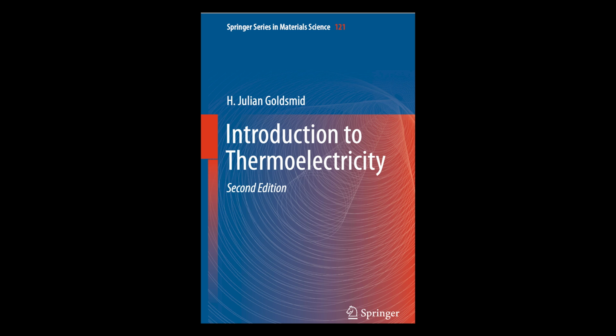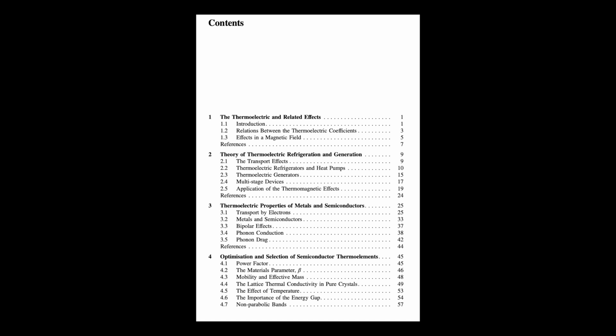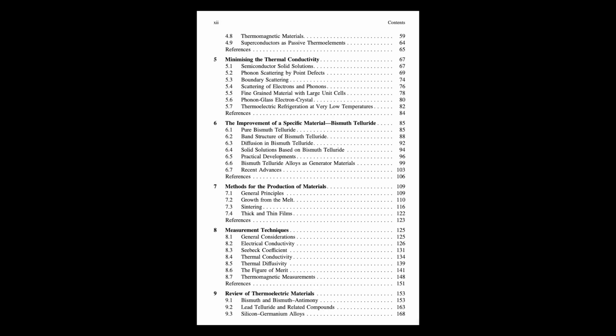Okay, let's zero in on a specific material that's been a real star. Bismuth telluride, Bi2Te3. What makes it so important? Bismuth telluride, yeah, it's the classic room temperature thermoelectric material. A real workhorse. It was one of the first semiconductors found with decent thermoelectric properties near room temp. And crucially, you can make both N-type, electron-rich, and P-type, hole-rich, versions with very similar, quite good figures of merit. Ideal for making thermocouples. Learning how to dope it precisely, like using iodine for N-type, was key. Back in the 50s, they got around 40 degrees C cooling below room temp just with Bi2Te3 couples.